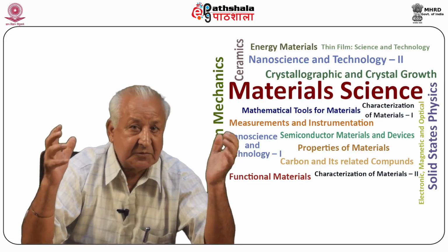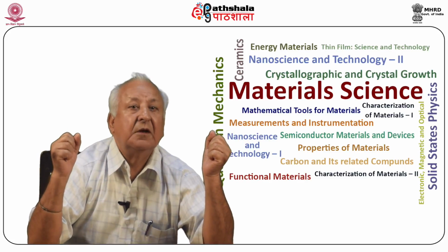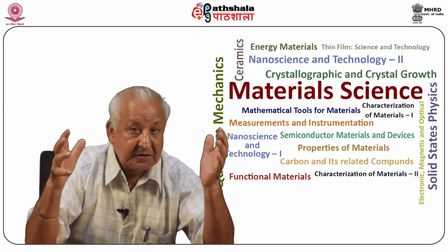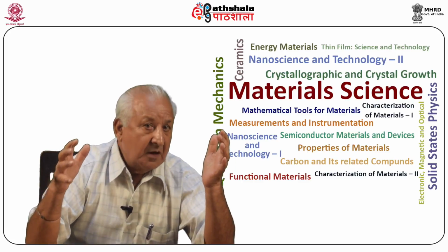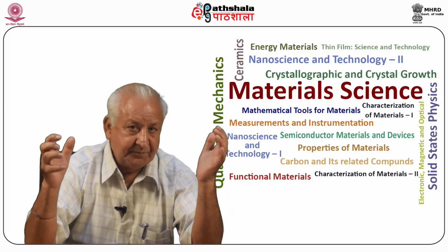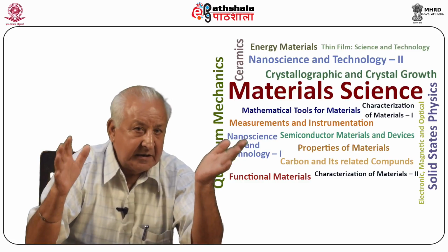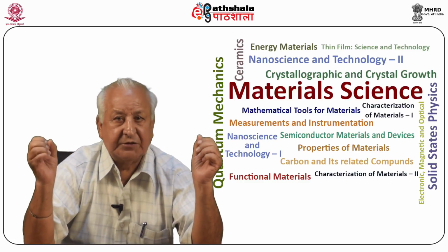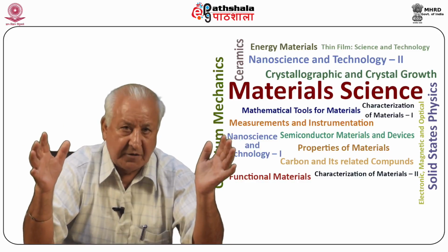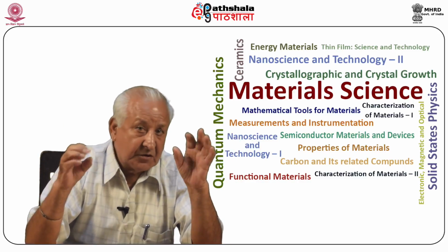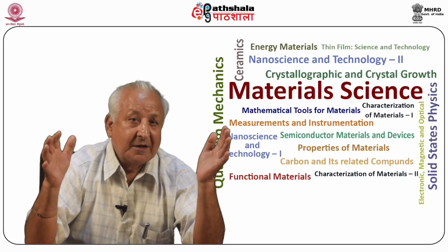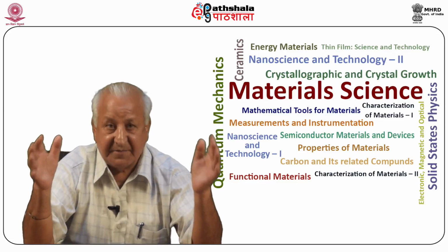This resolution is poor as compared to the resolution attainable in the case of TEM, that is the transmission electron microscope, which at best is in the range of 2 to 5 angstroms. Routinely operated TEM provides a resolution somewhere in the range of 10 to 50 angstroms. Comparing this with the resolution attainable with an optical microscope, it is at least 10 times better.